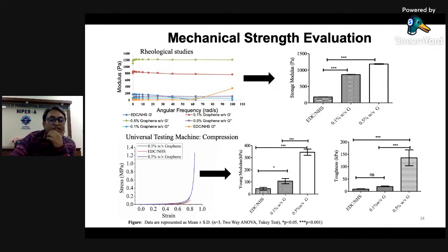But out of all these, if you further increase the stress, only one particular material is stable, and that is 0.5% graphene. All EDC-NHS and 0.1% graphene samples are broken beyond this point, so they cannot bear stress more than 0.1 to 0.2. But the 0.5% graphene can bear stress up to 1.2 megapascal.